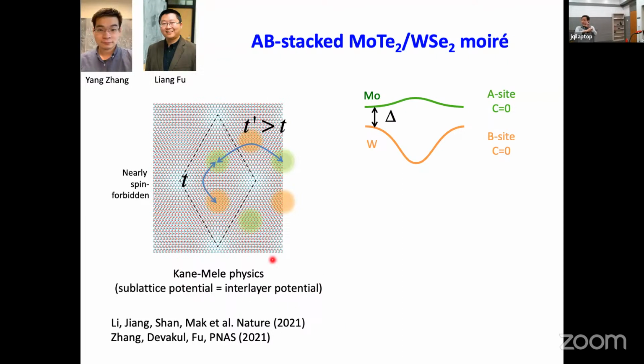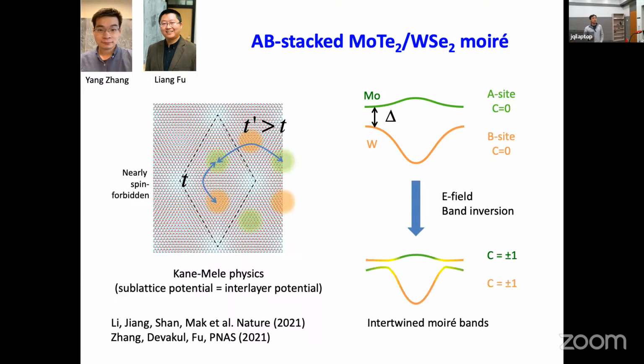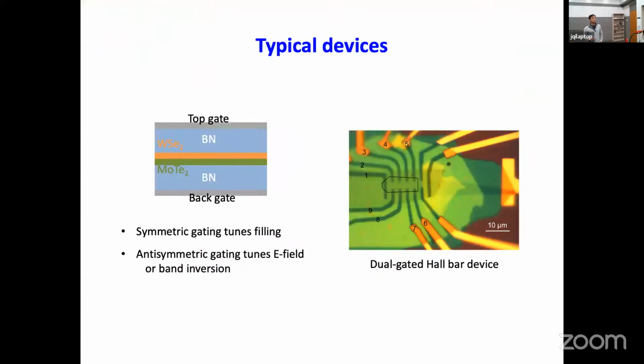And then the interlayer potential difference, which is controllable by the electric field, is equal to the A and B sublattice potential difference in this case. So you can imagine if I just apply an electric field, then I can introduce a band inversion for these two bands. I can make this charge gap here, delta, go negative, and then I may have some chance to create topological bands or Chern bands with finite valued Chern numbers.